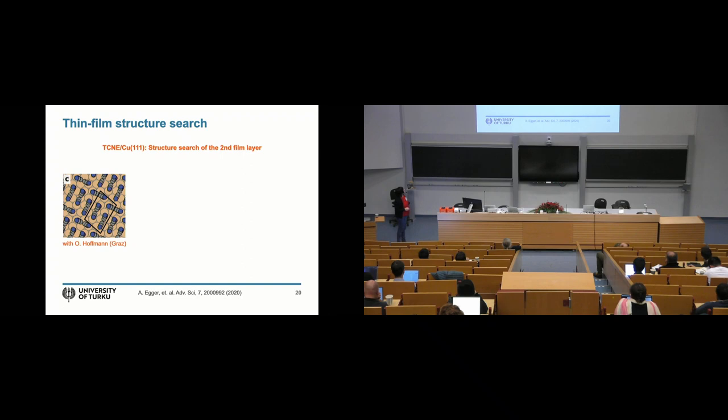I have to mention one nice example we did with Oliver Hofmann in Graz about thin films. Oliver's group has developed a sample growth method for studying the morphology of thin films that form on surfaces. This works on principles of identifying possible adsorption sites and then trying out different molecular adsorption configurations and then building combinatorially the films and finding the lowest energy ones. And they found that TCNE on copper-111 likes to adsorb standing up.